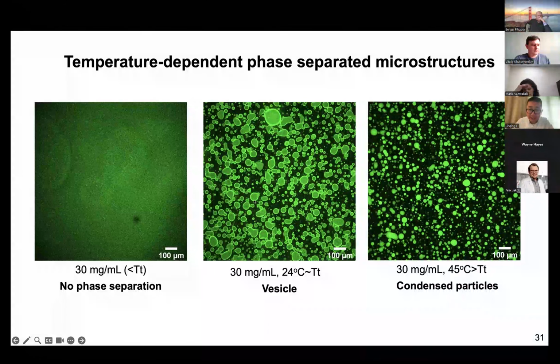which is quite unique and allows us future drug delivery applications. And if you continue to increase the temperature, the hydrophobic domains in the vesicle can continue to squeeze the water out of the inside of the vesicle and condense. Now we see completely condensed spheres, which are smaller in size at the high temperature when you form the hydrogels. So this is temperature dependent phase separated microstructures.